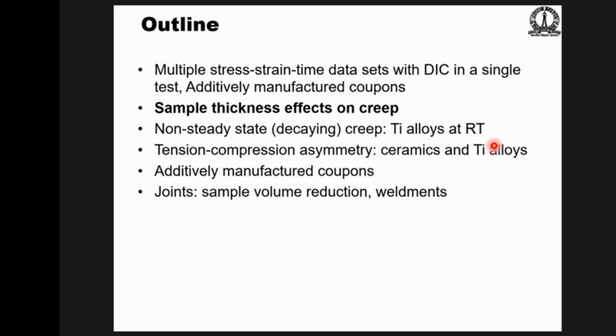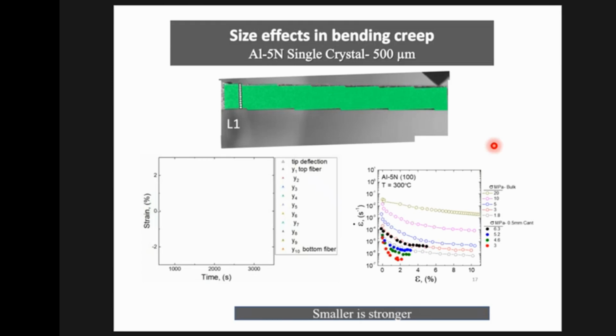Now let me address something which is a nuisance, namely sample thickness effects. If you're doing science, length scale effects are very interesting, but if you want to generate realistic data, length scale effects impose a limit on how small you can make your sample, because then you start getting information which can no longer be extrapolated to the bulk. So here's a test. I must thank Anton Paar, who makes these micro indentation systems. At their lab, they had very small beams. This beam is about 0.5 millimeter in thickness. And so we needed a facility for imaging and loading, which we availed of at their laboratory near Delhi.